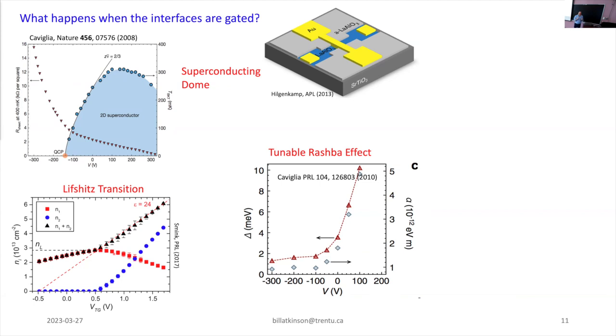So the original explanation invoked Hubbard physics, but I think that original explanation is wrong because the electron densities are nowhere near high enough for Hubbard physics to be important. So we wrote a paper where we explained it in terms of flexoelectricity. So essentially it's the coupling between lattice strains and the band structure that is giving you this unusual behavior. But I'm not going to have time to talk about this today, but I find this quite cool.